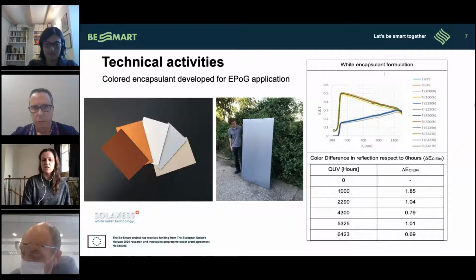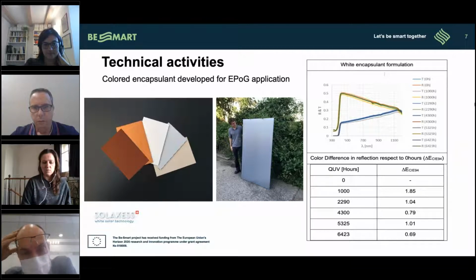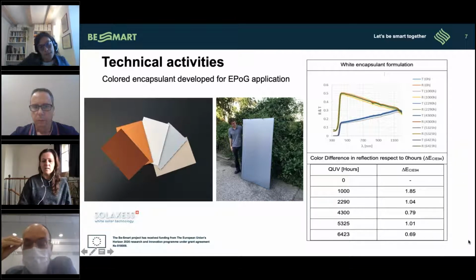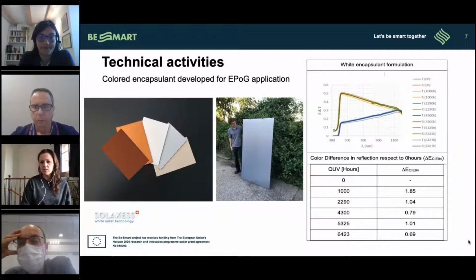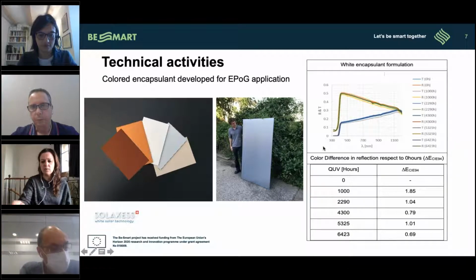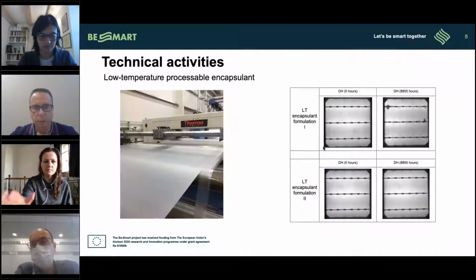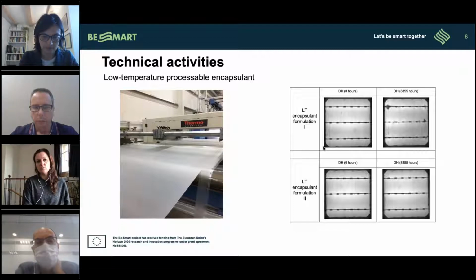Also, the big challenge of bringing this encapsulant into the module is to ensure its long life and reliability, especially under UV and temperature exposure. But the first results that we obtain are very encouraging in this way. We see that accelerated aging with UV light and temperature also brings very good results. So already the company Solaxess is implementing in their production line some of the developments that have been done in this project today.